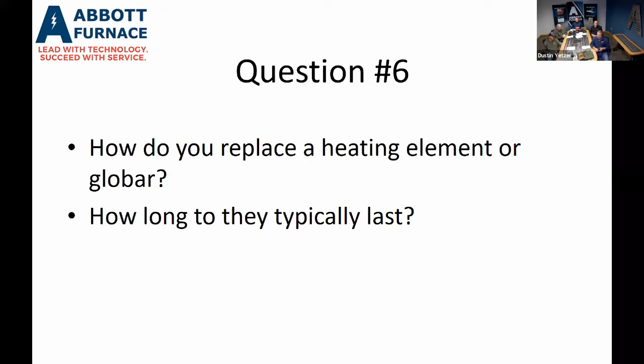But with glow bars, if you break one and replace just that one, they're usually connected 2 in series, so you start seeing an imbalance in your amperage and voltage. Old glow bars typically have their resistance increase as they wear. So when you put a new globar in with an old one, the new globar is actually going to work harder than the old one, and you'll start wearing that new globar out faster. One of the biggest phone calls I take is, I keep changing the same globar in my furnace. The reason is current takes the path of least resistance, so it's going to heat up that one globar the most in that bank.